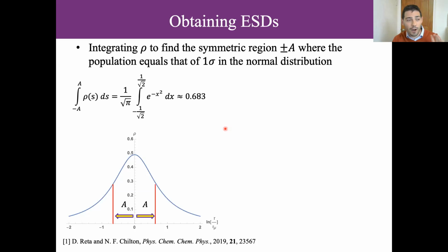And it turns out that the alpha parameters in most molecules are sizable. You know, we're talking 0.2, 0.3, which actually gives you about an order of magnitude plus or minus uncertainty on your relaxation rates. So it's important to consider these.